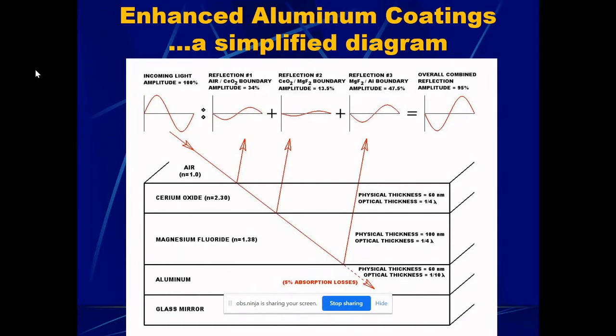Instead, we use magnesium fluoride as well as cerium dioxide, but we do the coatings in the opposite order to a lens. Let's go through what goes on. Light comes in, and it hits the cerium dioxide boundary first, which is very thin, quarter wave thick. It's got a very high index of refraction, 2.3. So we're going to get a huge reflection right off the bat, 34% for the cerium oxide boundary. The rest of the light goes through, and it hits the magnesium fluoride boundary, and we get another reflection. This reflection is about 13.5%.